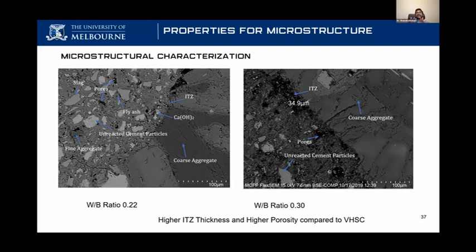The pictures you are seeing here are SEM images with EDX. EDX finds the minerals or the chemical composition as well. That's why you see different colors. If you zoom into the concrete or the cement paste, this is what we see. This is the aggregate, and that's the ITZ here. A very thin ITZ for very high strength concrete, but for normal strength concrete you will see a thicker ITZ. Then you will see the fly ash particle here, the circular particle. We know fly ash is circular, like ball bearings.